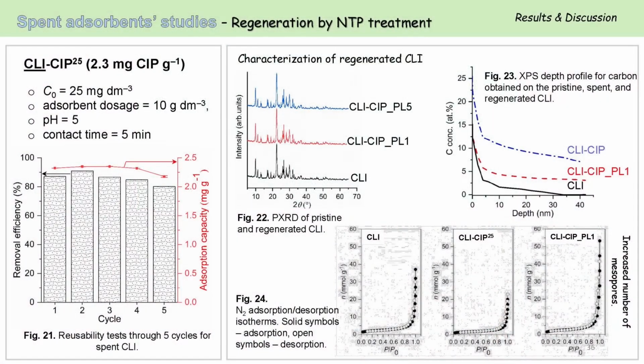Then the characterization of the regenerated clinoptilolite was performed to see if plasma had some impact on the clinoptilolite structure. The PXRD results for the pure clinoptilolite and the regenerated clinoptilolite after the 1st and after the 5th regeneration cycle showed that plasma didn't have any impact on clinoptilolite crystallinity. Also, the nitrogen adsorption-desorption isotherm measurement showed that after the plasma treatment, the number of mesopores increased. And for the XPS depth profile of carbon, we can see that the loaded clinoptilolite has, of course, the highest amount of carbon, while it decreased after the plasma treatment.